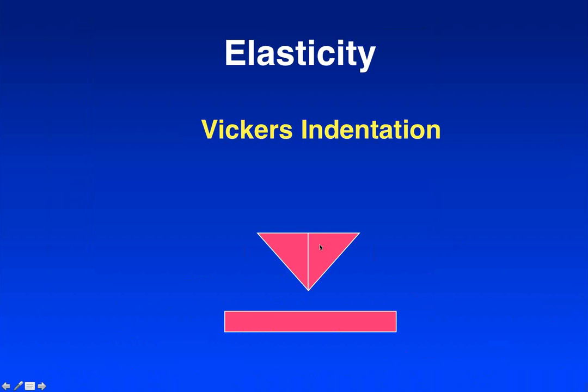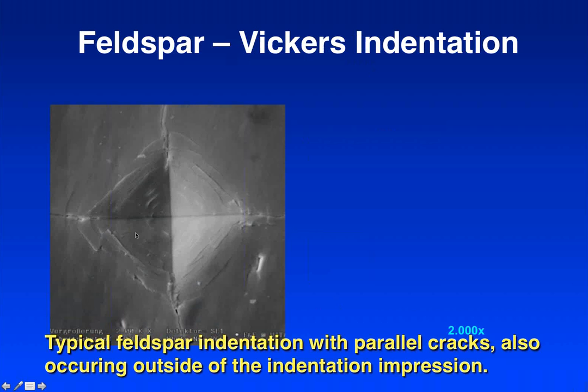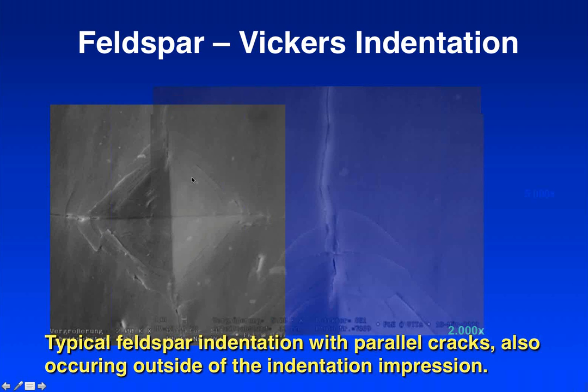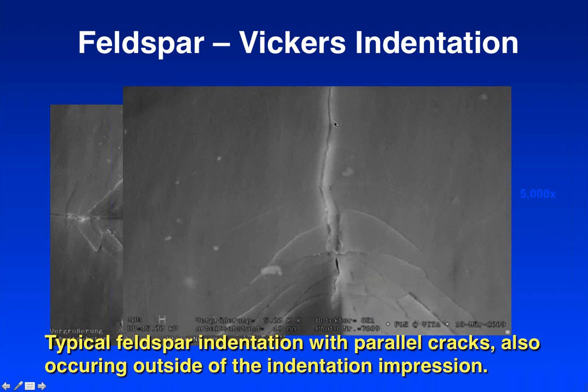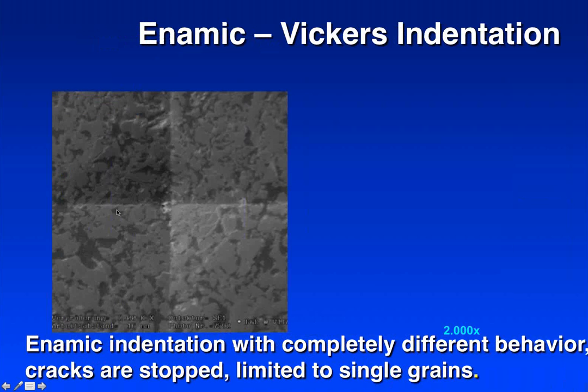A good example of the stiffness of the material, testing it, is doing this indentation testing. And this is actually a diamond with a very sharp point that gets embedded or pressed into our material down here, and it creates an indentation in the shape of the diamond. So it's like a diamond. And with a ceramic material, conventional ceramic, you tend to get cracking at the edges of this indentation, and the cracking tends to proceed through the material for a fairly great distance. If we do the same thing to Enamic, you don't see the same type of cracking damage that you get with a conventional ceramic.